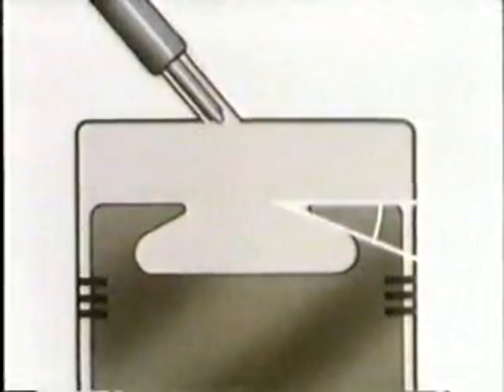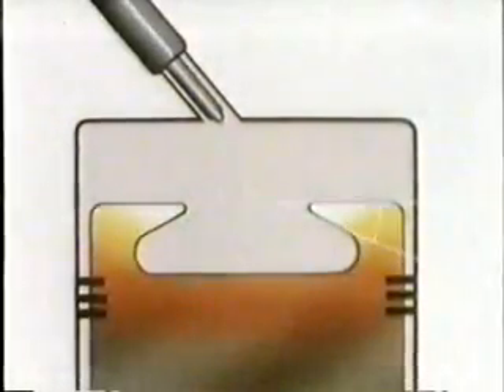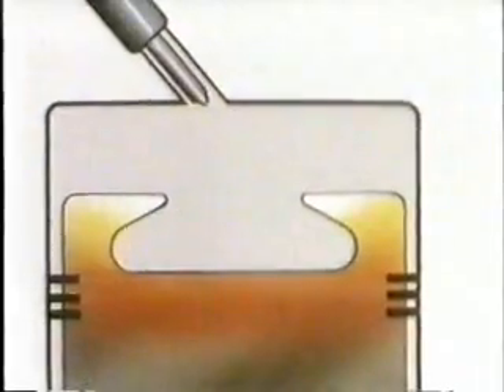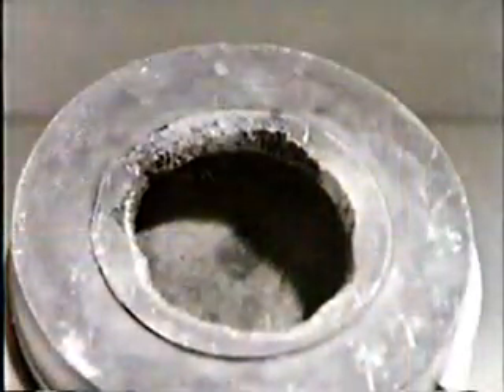As far as the mixing of the air and fuel went, the best results came from a bowl with an acute angle to the lip. But with that shape, heat built up around the lip, and using conventional aluminium, the heat was not easy to dissipate. A number of alternatives were tried.